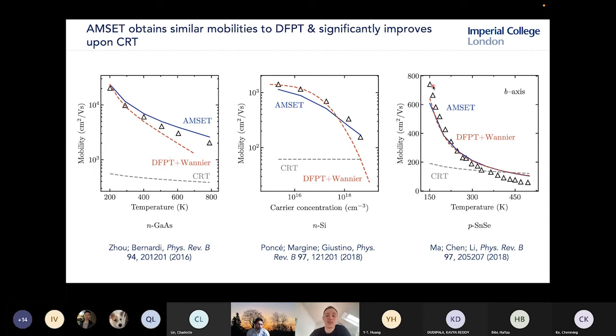The other thing which is nice is that we can take into account anisotropic properties. Tin selenide is relatively anisotropic. Here I'm just plotting the results for the b-axis, and you can see it agrees pretty nicely. I'll highlight this gray line here, which is the constant relaxation time result. You can see that with this approach, you get these results wrong in both magnitude and also the temperature and carrier concentration dependence. So it's really not a robust theory to use.